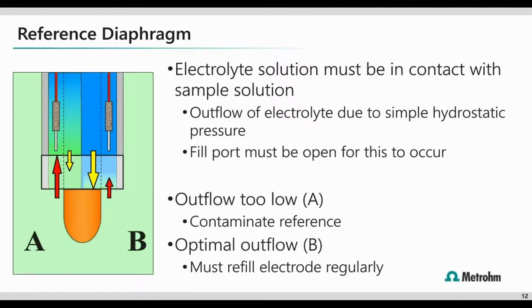So if we focus on side A, here, this is what happens when we let the electrolyte level drain to very low levels. When we put that electrode into the sample solution, the pressure on the outside of the electrode is greater than the pressure on the inside. So what happens is we have the sample creep, follow that red arrow, creep up into the inside of the electrode. And then what happens is we are contaminating the reference chamber and ruining the electrode beyond repair here.